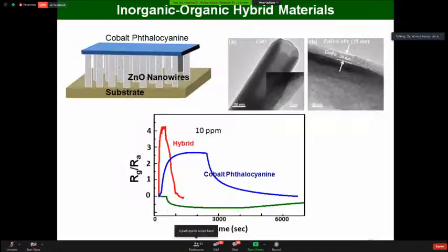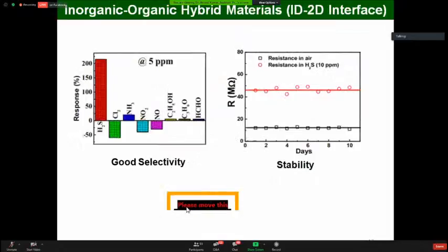Now, as an example, you can see here that ZnO is an inorganic metal oxide, and this is the nanowires of zinc oxide, and we have coated cobalt phthalocyanine over this zinc oxide. This heterojunction shows better sensitivity as compared to the individual materials. You can see in this graph the response curve for the hybrid material. This blue one is the response curve for cobalt phthalocyanine, and this is for the nanowires. You can see that the hybrid material shows better sensitivity, as well as faster response and recovery time, as compared to cobalt phthalocyanine and zinc oxide nanowires.